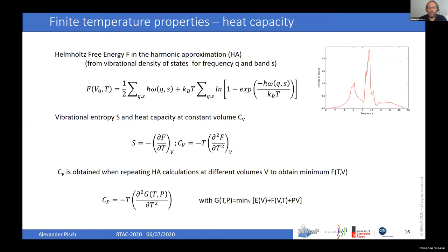And if I want the heat capacity at constant pressure, then I just have to calculate a series of Helmholtz free energies at different volumes. And like this, I can calculate the Gibbs energy. And from the Gibbs energy, as given here, the second derivative with respect to temperature, I can calculate the heat capacity.